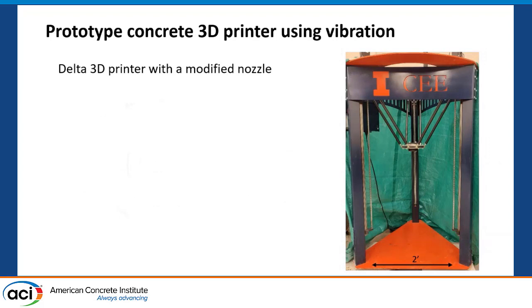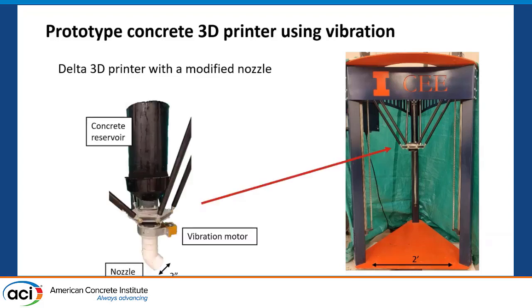Moving forward, I actually wanted to 3D print something. Back home in Illinois, we have a 3D printer which is meant for clays, paste, and mortar — not really for concrete. So I had to build something. I have a prototype where I have a PVC nozzle, two-inch diameter, with a vibration motor attached to it and a concrete reservoir, which I'm manually filling with concrete to 3D print.